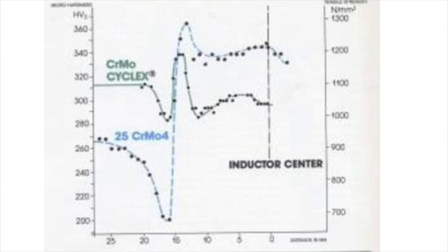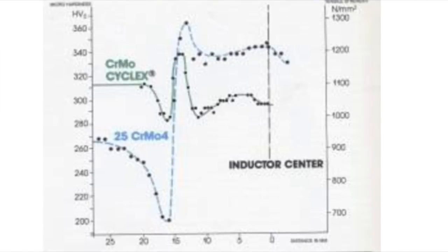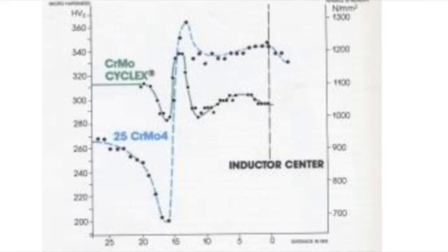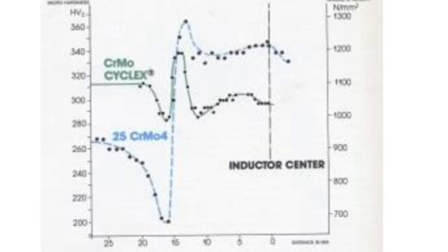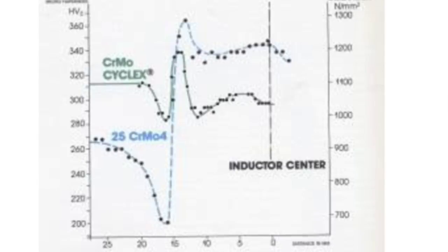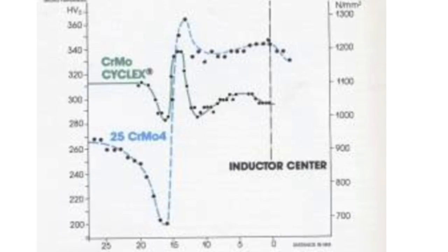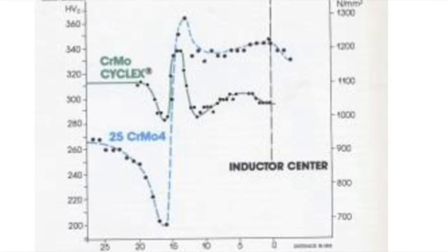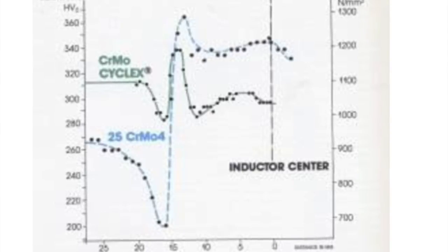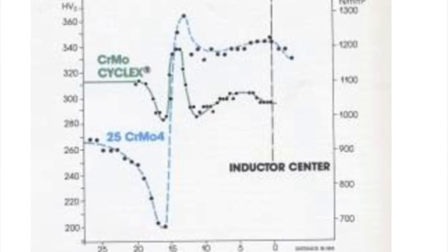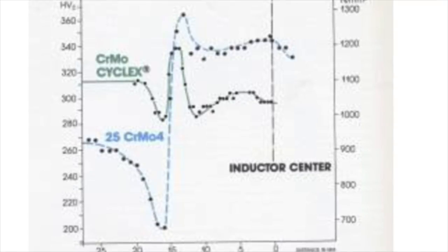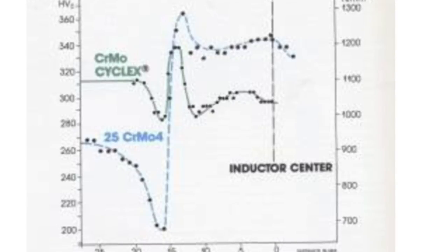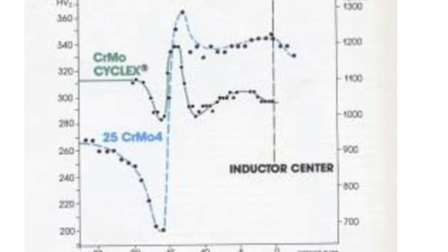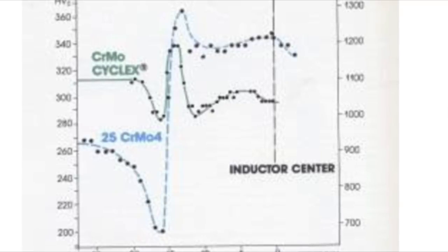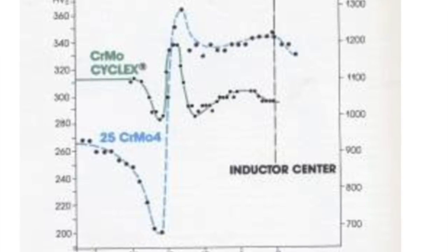So what's happening is you'll see that it goes up, it gets quite a bit harder, and then it drops, and then these graphs don't actually show it, but it actually returns to the starting point of what it initially was. So what you can see with this graph, though, that's instructive, is that all the materials, when you weld them, both get harder and they get softer. So there's a spot where they get softer, and the first thought, if you're an engineering guy, is, oh, okay, that's where it's going to fail because it's going to be weaker. It doesn't turn out that way, but we'll talk about that in a minute or so.